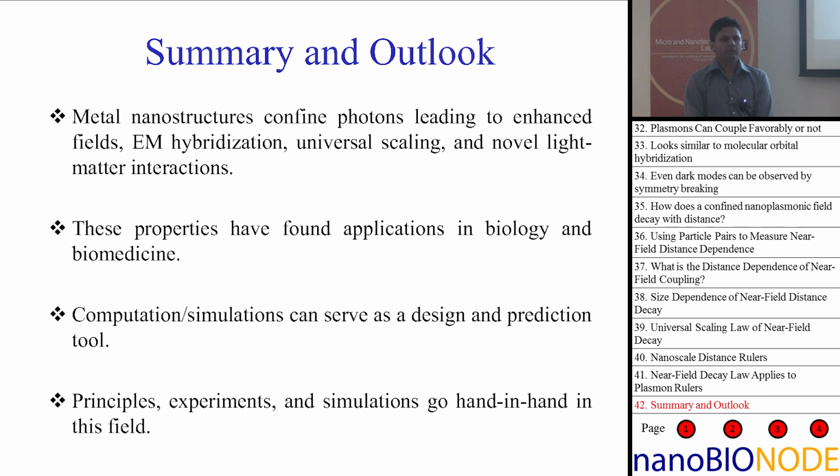So I will tell you, one of the simplest renditions of that would be if you take a 10 nanometer particle, I showed you actual data. They mostly absorb light, don't scatter much light. Small particles absorb light, right? If you assemble a whole bunch of them together, in that volume fraction type method, the scattering increases. So we talked about shifts. What happens to plasmon resonance maxima as a function of particles coming closer? You can also look at scattering and absorption. And it turns out, as you couple these particles together, their scattering cross-section increases. So that could be one way to shift from an absorptive configuration to a scattering plus absorptive configuration. Some of the absorption still remains. That's a very neat thing. I guess that's one other parameter you can tune.